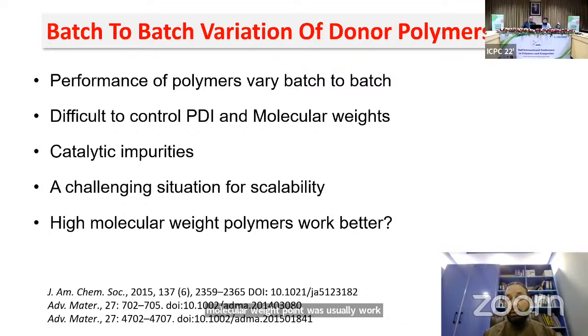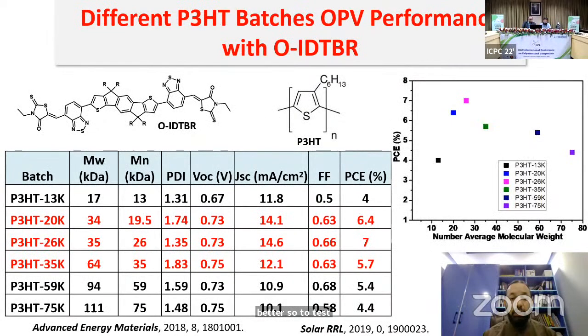To test these things, we used six different molecular weights of poly-3-hexylthiophene, and we tested them with the non-fullerene acceptor synthesized in our lab. What happened is that we didn't see good results with the low molecular weight or the very high molecular weight fractions. Instead, we saw very good results from the medium-sized molecular weight polymers, showing very good efficiencies of about 7%, even for a binary blend. Instead of ternary, we were able to get about 7% from a binary blend with careful choosing of the right batch.